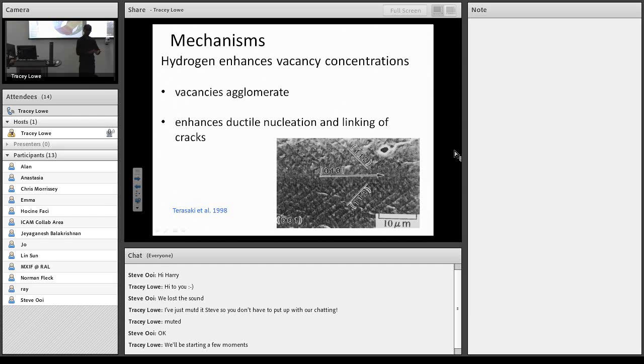And because there's a large number density of these voids, therefore you more or less see macroscopically brittle failure. The larger the number density of voids, the less is the ductility, because they don't have to grow much before they link up. And again, you would require a mechanism where hydrogen produces this effect in some localized region where there is a concentration. I don't have the original paper of this, but the paper describes that if you look at this by atomic force microscopy, you see strings of microscopic voids, which would be consistent with that. So something causes the hydrogen to localize, for example, a stress concentration, and then you create a larger than equilibrium concentration of vacancies, which then condense to give you these microscopic voids, which when you pull, link up by ductile failure. Okay, so the fracture surface will show you ductility rather than cleavage.